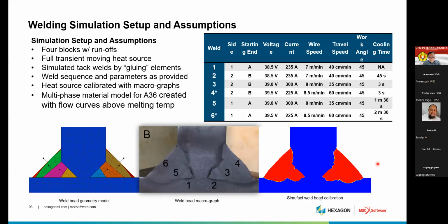Okay, and with this we are getting this kind of macrograph. So for these 6 welds, we have inputs like the voltage, current, the wire speed, the torch velocity, the torch angle, and the cooling time between the 2 welds, basically. Okay, and with this setting we are getting this kind of weld pool, and when we compare it with the macrograph, it has come up perfectly.